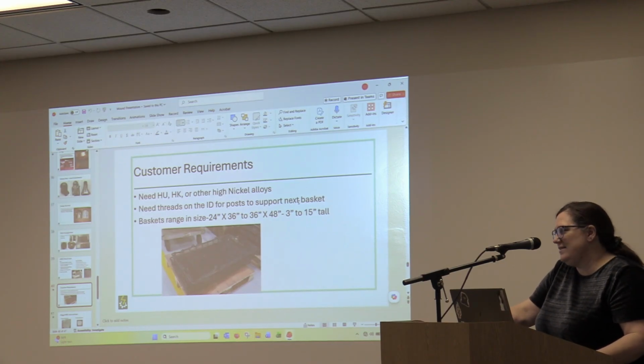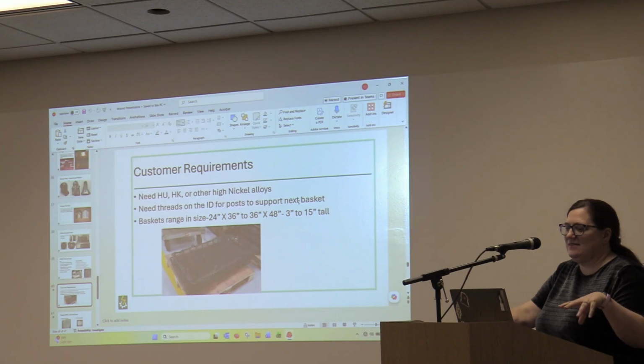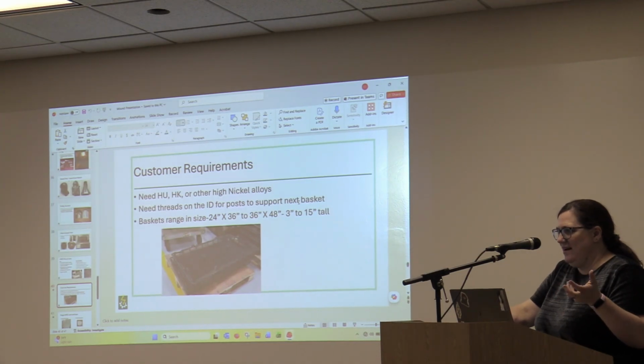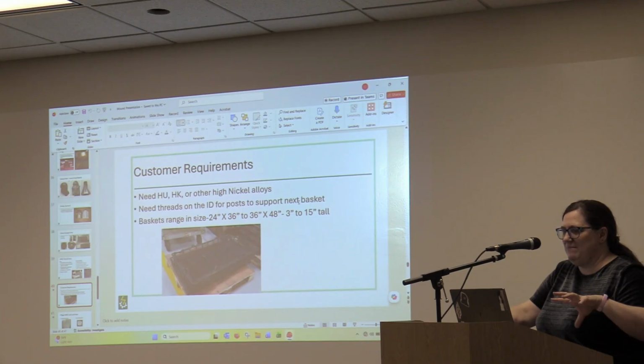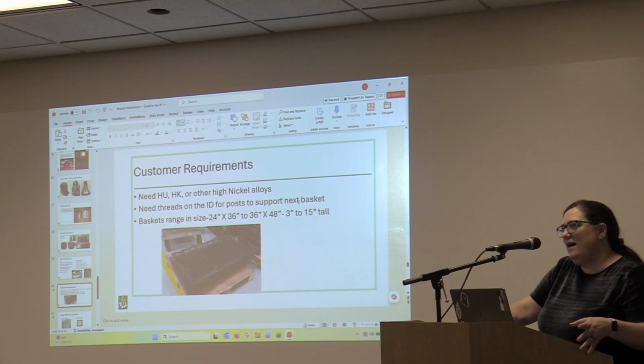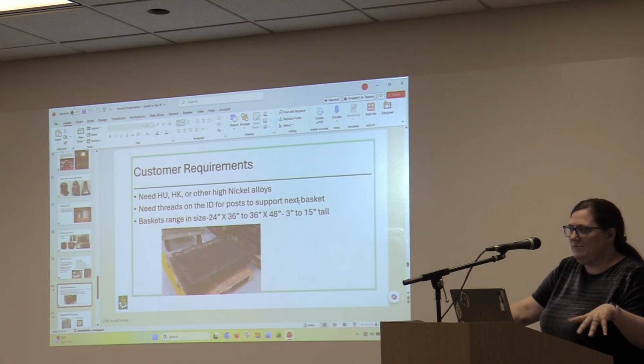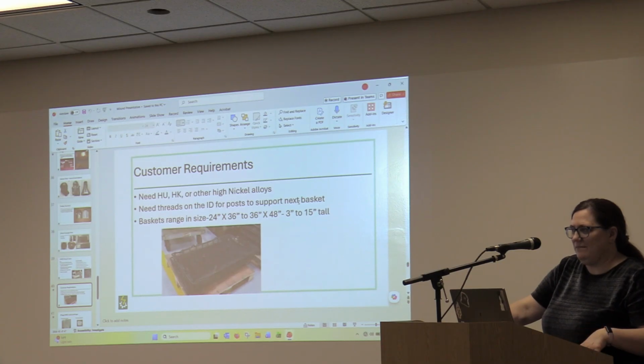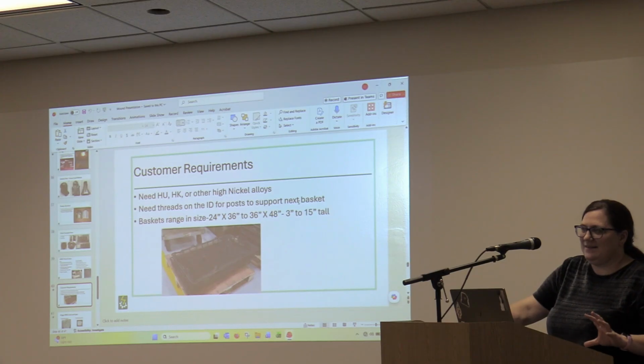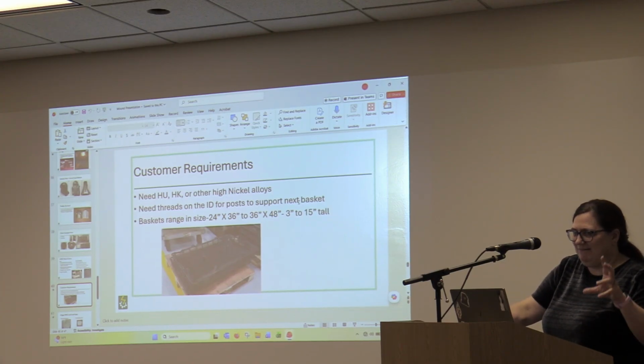So what we think is happening is the reason we don't see an issue with ash is that ash is a remnant of burning, and the burning doesn't happen in the mold, it happens outside. So there's not enough oxygen and then that polymer gas gets pushed out. What we do see is about 0.01% carbon absorption in the metal. So people ask us for 316L, that typically is very difficult to get because you can exceed that carbon content. Thank you.